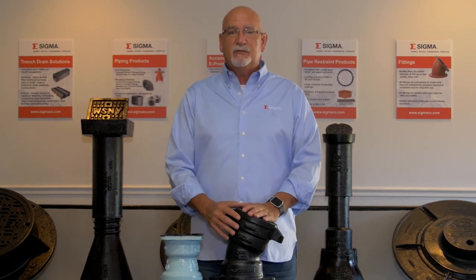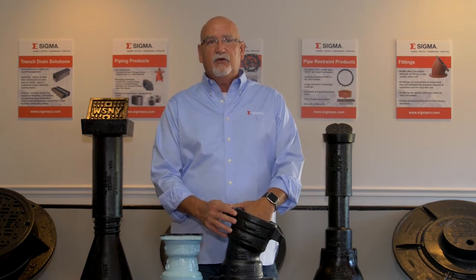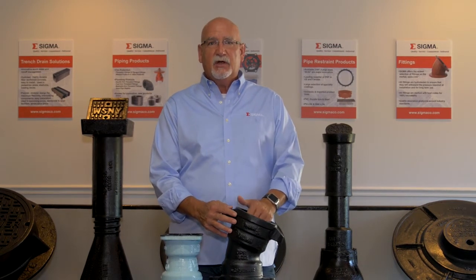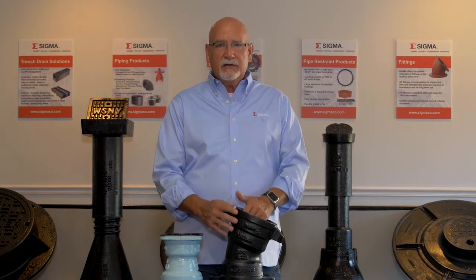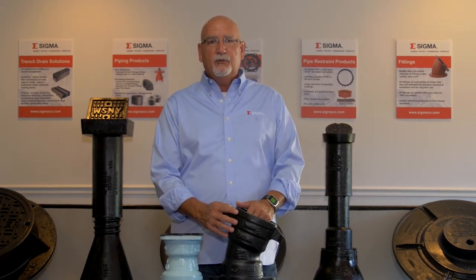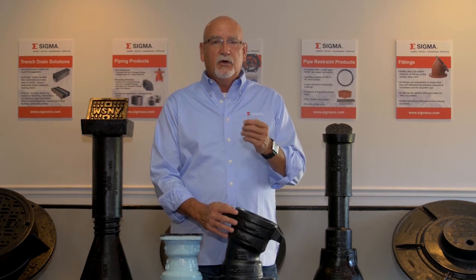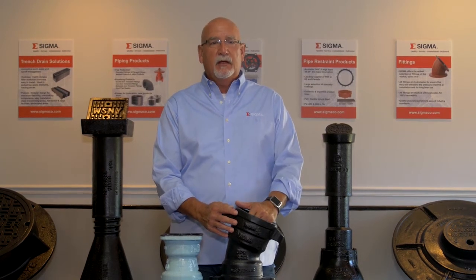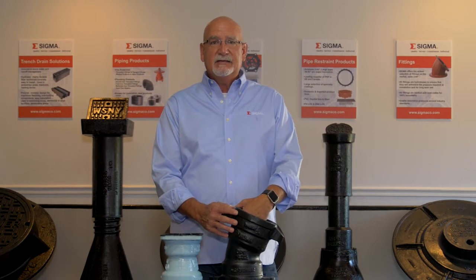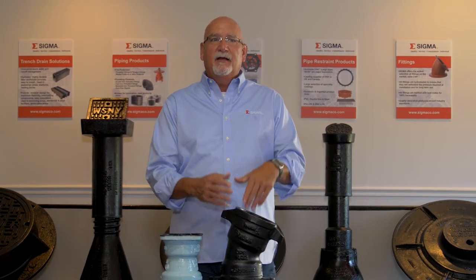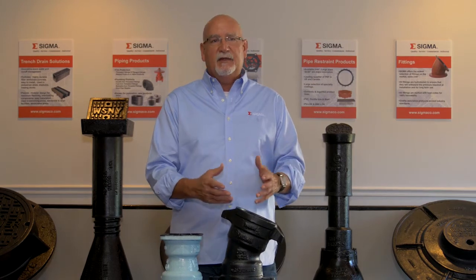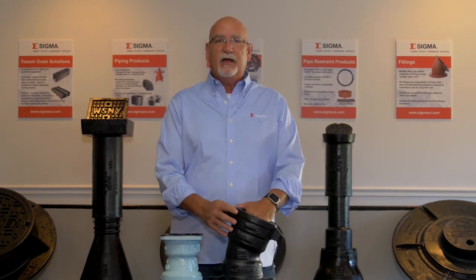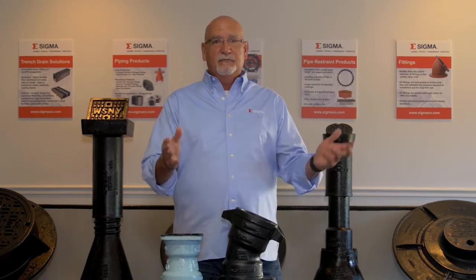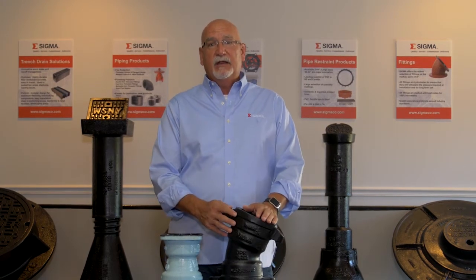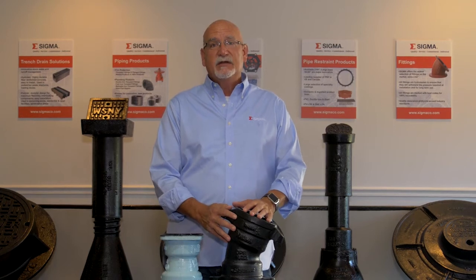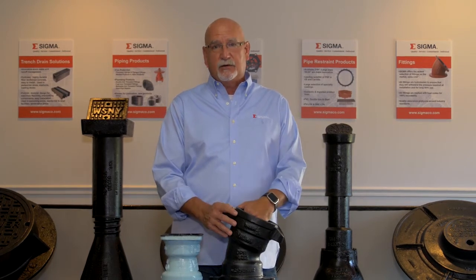The reason that cement was initially introduced into ductile iron pipe and fittings is because clean water, even clean water, has minerals, and those minerals will actually cause a corrosion on the surface and a buildup. And so the cement protects the inside of the fitting from a corrosive buildup. And that sounds a little backwards, because typically when people think about corrosion, they think about something going away, almost evaporating. But with water inside of pipes, the minerals actually deposit as a result of corrosion.